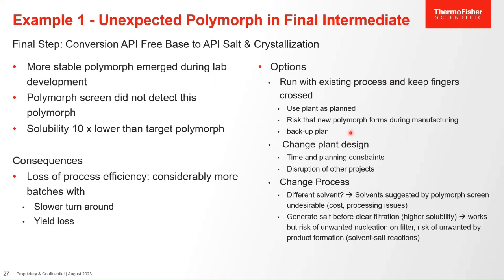and we did have a backup plan for the case that the wrong polymorph was formed in manufacturing. We were very lucky. A number of batches worked as planned. And in the very final batch, we did find the new polymorph of the final intermediate, and the backup plan kicked into action. And that was simply a portion-wise dissolution and clear filtration, followed by solvent removal. And then everything carried on as initially planned. This is not something you want to happen, but unfortunately, there is no way of protecting us from this, for reasons I mentioned earlier. You can never predict the most stable polymorph. You can merely risk mitigate.